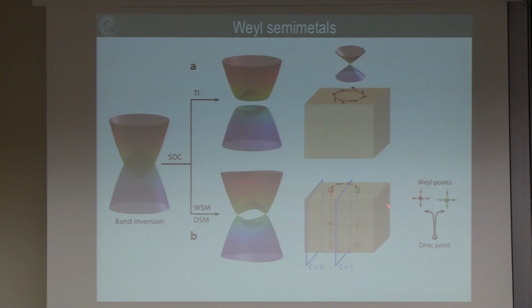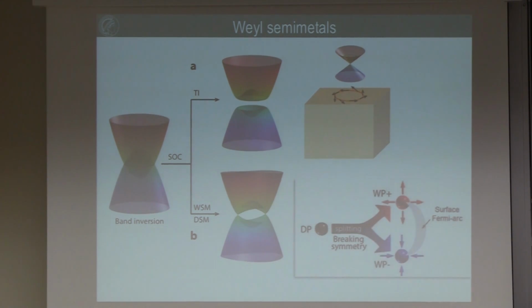So a Weyl semi-metal is topological between the Weyl points, and these Weyl points again have bulk properties like the symmetry of a topological insulator, leading to a certain surface state, which here are Fermi arcs. These are not a full Fermi surface on the surface of the crystal, so the Fermi arcs are connected on the other side, giving very interesting properties in this material. This is a symbol of how the Fermi arcs on the surface connect the Weyl points.